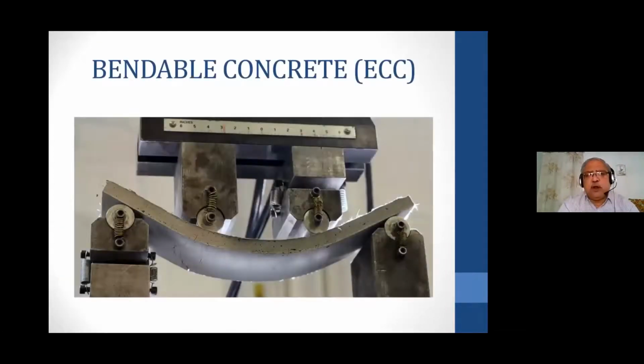But now, see that even at this particular level, you will find some cracks have started generating. Assume now it is a straight flat, which is the normal position. See now how much deformation it has undergone without generation of any crack. And even though this crack is there, I can still load it more, and only then will the crack propagate, not to a sudden brittle failure, but it will lead to an elastic type of